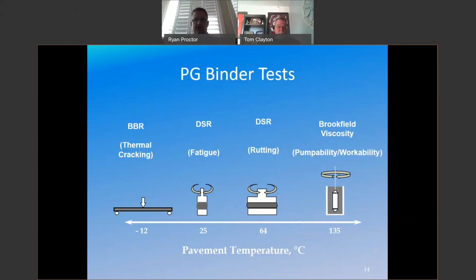So that brings us to PG binder testing. There was a significant amount of work from the FHWA, the Asphalt Institute, paving associations, contractor. I mean, our whole industry was really involved in this effort in the late 90s, and it was to get the performance-related tests back into the system. So if you look on the bottom of that slide, right above pavement temperature, you'll see that we're looking at tests that cover, and minus 12 is just an example, we could look at tests that cover the range from minus 30 degrees or minus 36 degrees Celsius up to tests that are even higher than 135 degrees Celsius. And the goal is to find out how the binder will perform at those different stages.